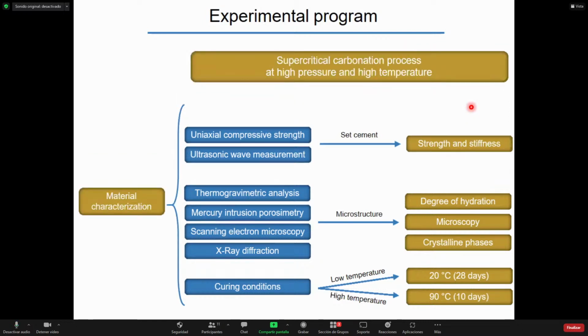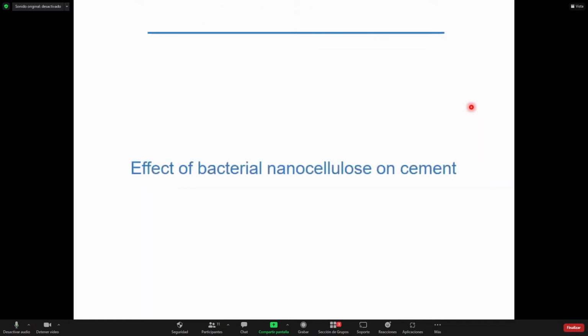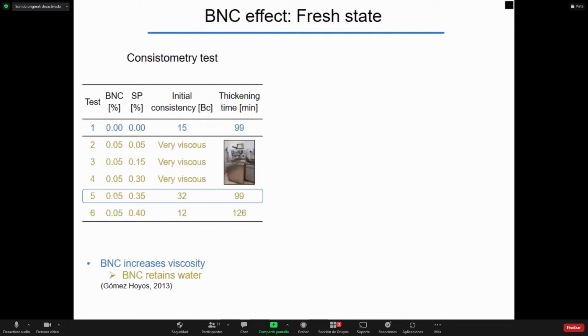After this, we carbonated our samples at high pressure and high temperature for a period of time. And we performed more or less the same tests as before, considering both curing conditions of low and high temperature. Now I'll present to you the effect of bacterial nanocellulose on cement. When we first added bacterial nanocellulose to cement, we saw that viscosity increased. This means that the bacterial nanocellulose was retaining part of the mixing water.